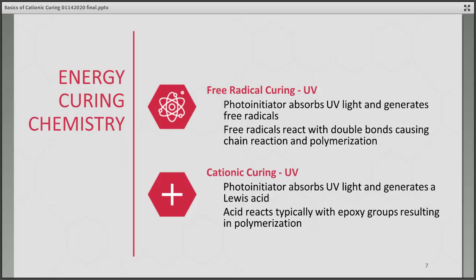In free radical cure, you use a photoinitiator. It absorbs UV light and it generates your free radicals. So that's how you generate and kick off your polymerization reaction. The free radicals react with double bonds, causing chain reaction, and you get your polymerization and your final ink or coating. In cationic cure, it's pretty much the same process.